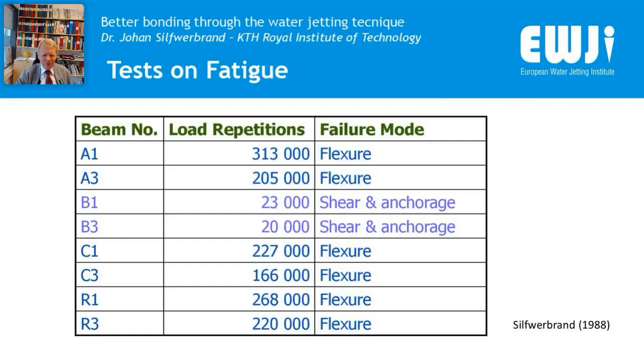And then also very interesting in this test series was that when we made the fatigue test, you can see that we received flexure failure for A, C, and R beams, but we received shear failure for the B beams. And you can also see that the number of load repetitions to failure was 20,000 for B beams and 200 to 300,000 for A, C, and R beams. So also here we can see that it is a very obvious result.